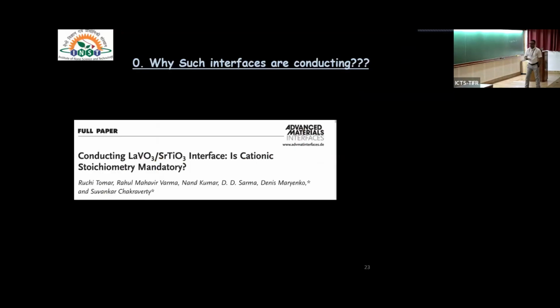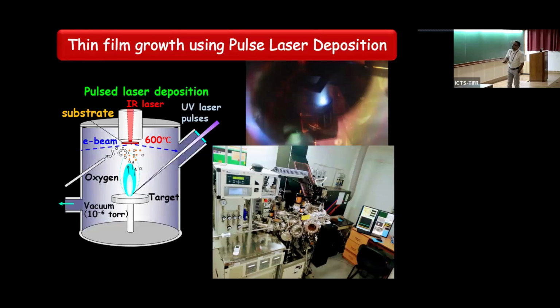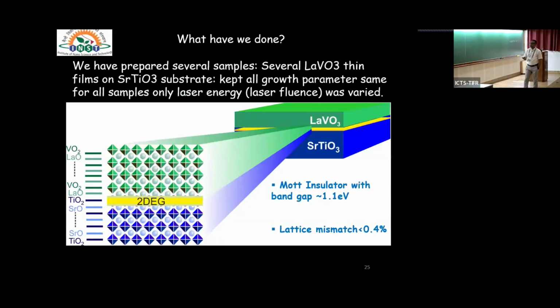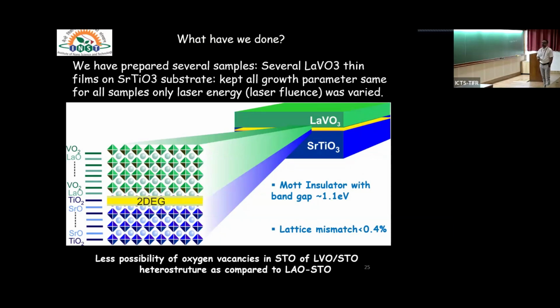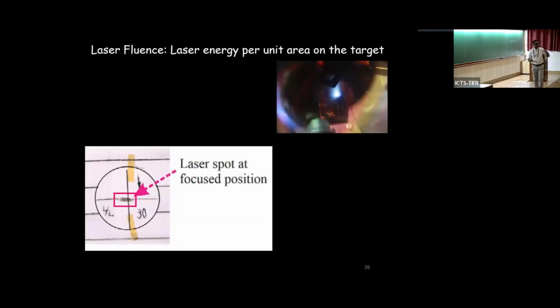So this is the paper we are going to talk about. This is the pulsed laser deposition system we are using. What we are doing is the following. We are preparing lanthanum vanadium oxide on top of strontium titanate, and it has a lattice mismatch of less than 0.4%. This also means less possibility of oxygen vacancy in the system, because vanadium is not as bad as aluminum, and the growth condition is much milder than lanthanum aluminate. This is the actual laser spot on top of a target.